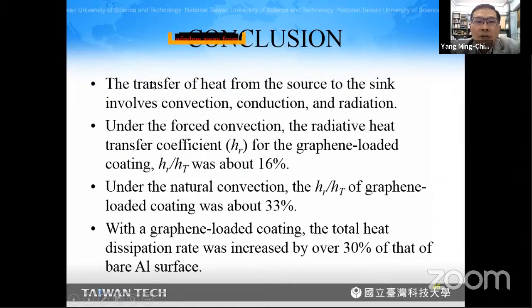Okay, the conclusion of this research: the transfer of heat from the source to the sink involves convection, conduction, and radiation. Under the forced convection, the radiative heat transfer coefficient for the graphene loaded coating was only about 16%. Under the natural convection, the ratio of the graphene loaded coating was about 33%. And with the graphene loaded coating, the total heat dissipation rate was increased by over 30% of that of bare aluminum surface. Therefore, in our research, we did discover that graphene loading did improve the heat dissipation by over 30%. Okay, this concludes this talk.